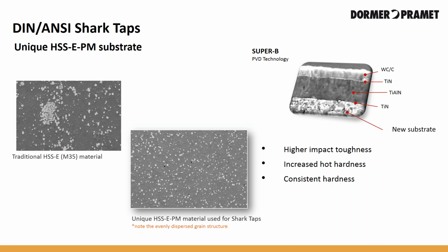Our Super B coating is applied to our blue Shark taps. This is a hard lube coating in which the high hardness and temperature resistance of TiAlN is combined with the outstanding frictional and lubrication properties of a WC/C, which is tungsten carbide carbon surface layer, to allow for smoother chip flow. It's especially beneficial when threading tough, long chipping, heat-resistant materials such as stainless steel. The Blue Shark designs are the only DIN ANSI Shark taps that offer this type of coating on top of the HSS PM special substrate. Blue Shark taps offer excellent performance even when cutting temperatures reach almost 1500 degrees Fahrenheit.